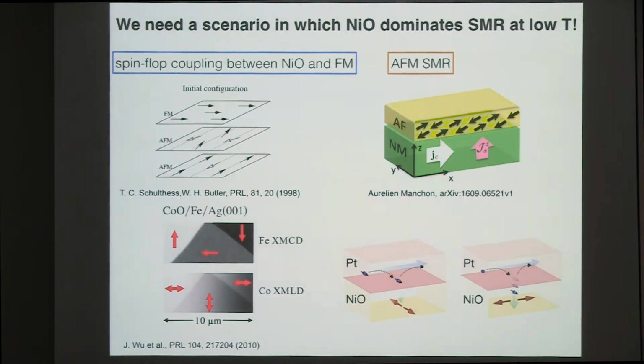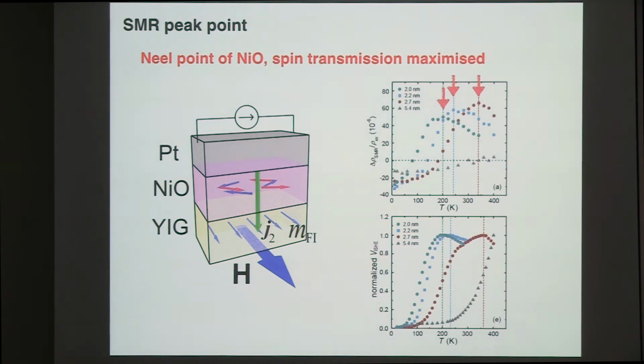So another very important point, I think, is also already reflected in Moreno-san's experiment. That is, you don't actually need a ferromagnet. If you only have an antiferromagnet system, you can still have SMR, because the SMR effect does not really require a ferromagnet. It just requires that you have a determined axis of the spin. So if it's a bipolar, like the antiferromagnet, it should still work, right? Combine these two, and actually we come up with a kind of explanation for everything.